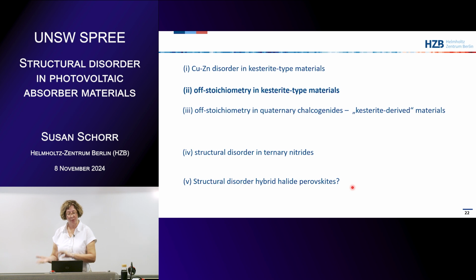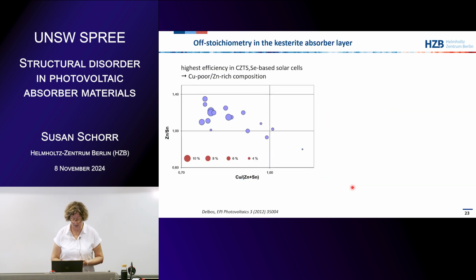So from this disorder now going to the point defects, I would like to show you the off-stoichiometry in the kesterite type materials. Well, this is a figure from an older paper from 2012, and it shows here two cation ratios. The copper over zinc plus tin ratio is here, and the zinc over tin ratio is here. Here is the stoichiometric composition. And the author of this paper summarized this here to show that the highest efficiency in kesterite-based solar cells is a copper poor and a zinc-rich composition.